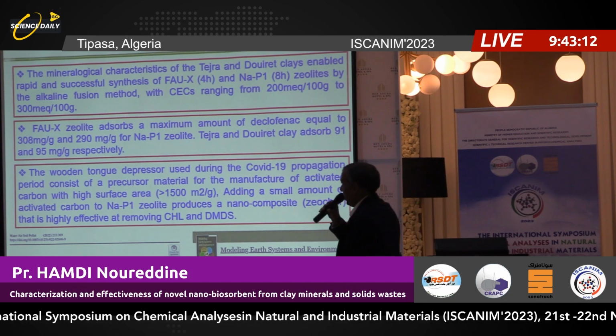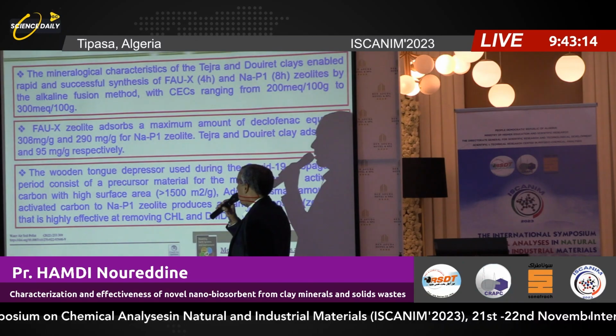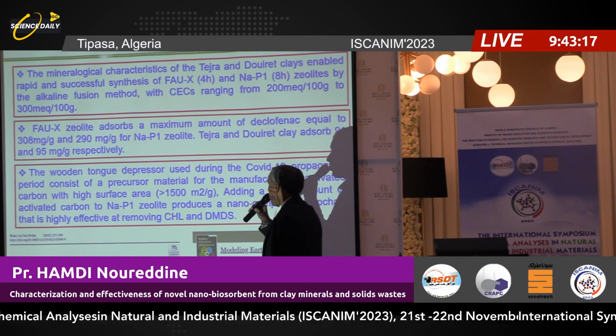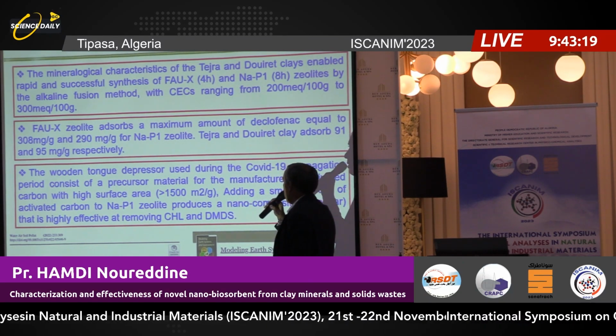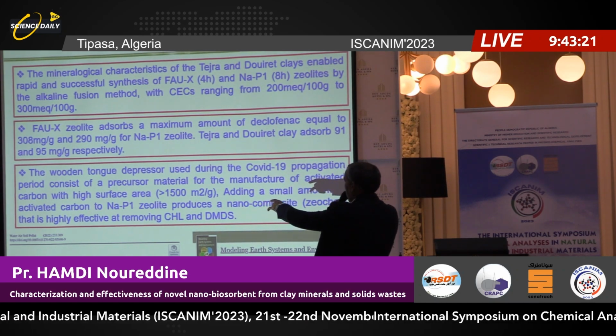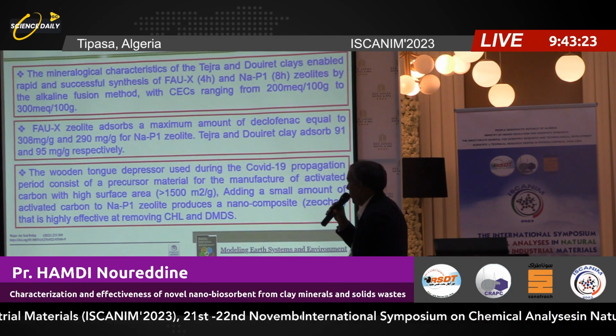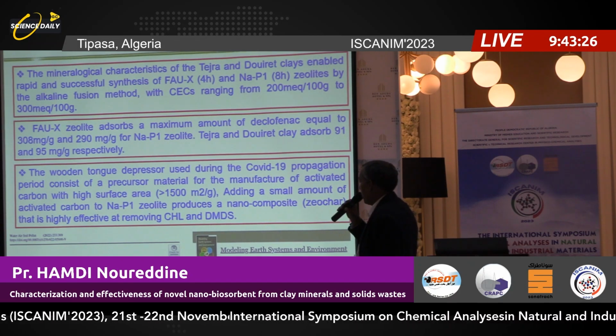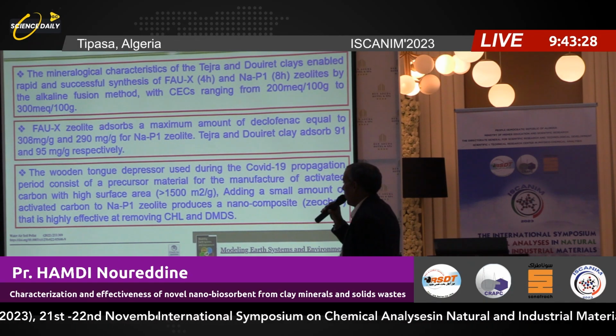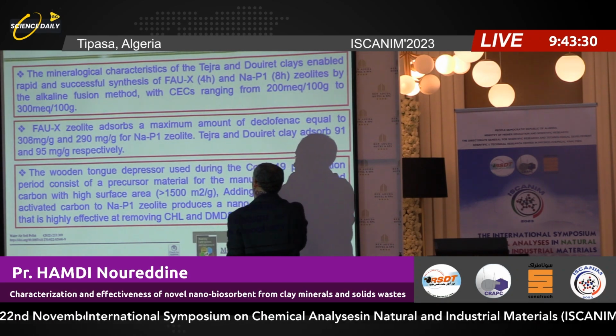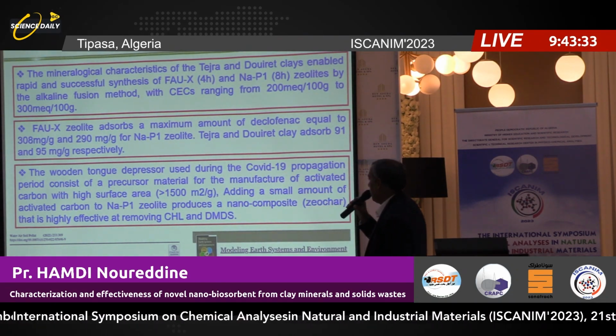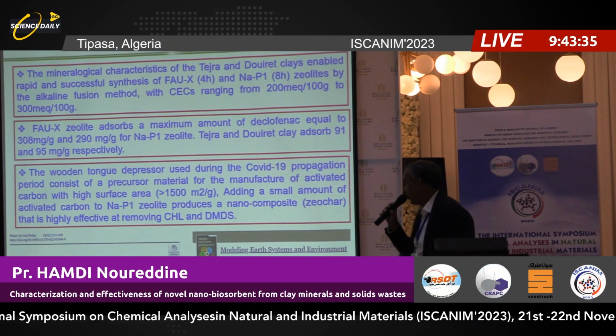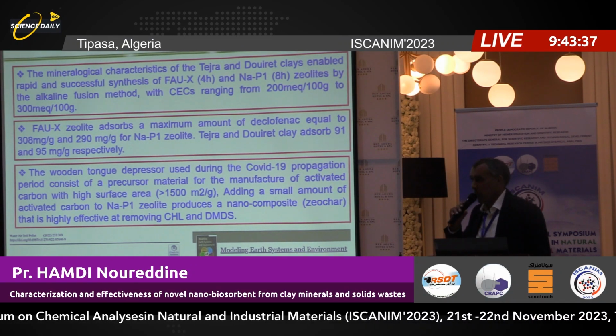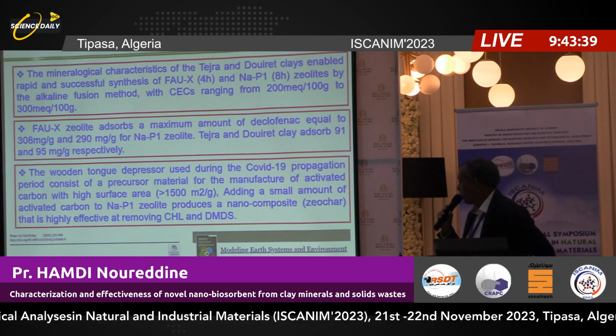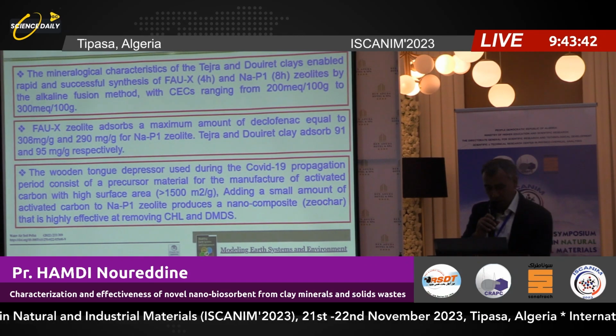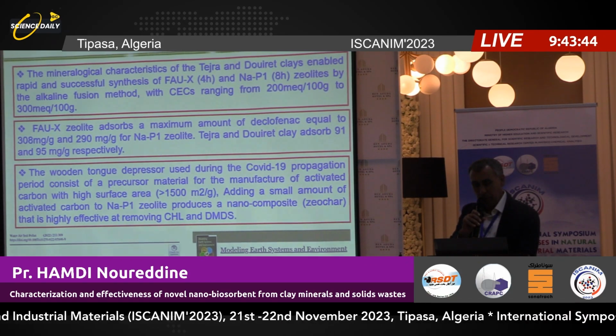In the second case, when we use the composite activated carbon and zeolite, in the case of the adsorption of 5-FU, we found that the surface area is very high, about 1,500 square meters per gram, and the adsorption capacity is very, very high compared to zeolite. This is published in two famous journals in the environment.